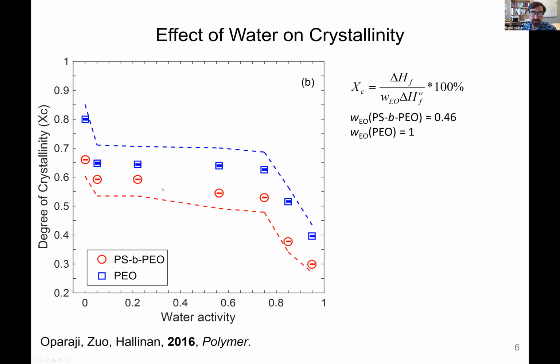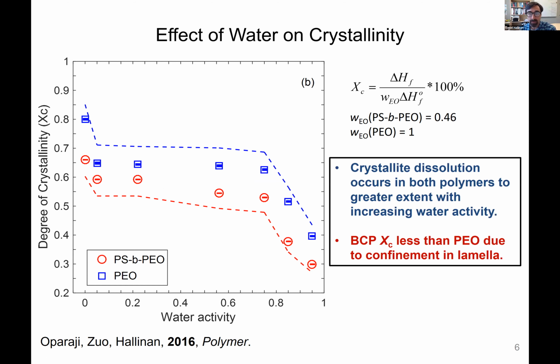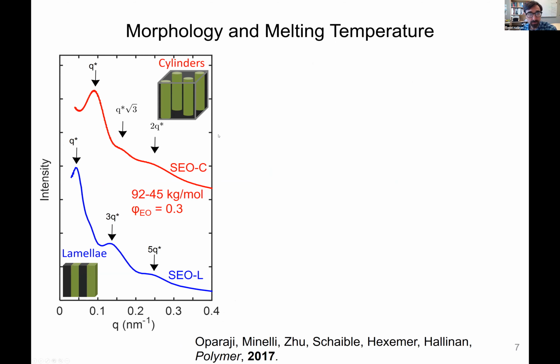Crystals are expected to be impermeable, so lower crystallinity should equate to better transport of water through the material. We also looked at another morphology of another block copolymer we synthesized: 92 kilogram per mole polystyrene, 45 kilogram per mole polyethylene oxide. So it's a majority polystyrene.